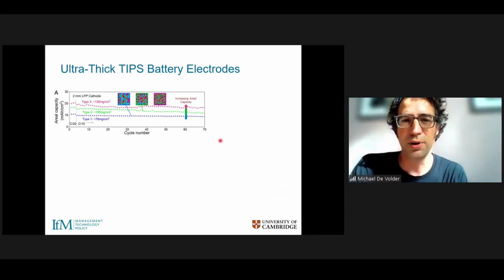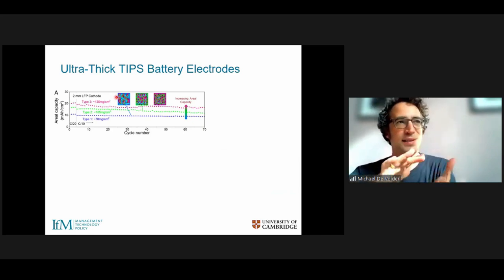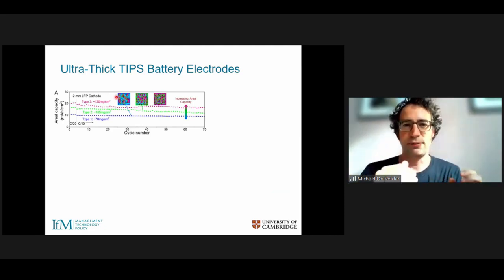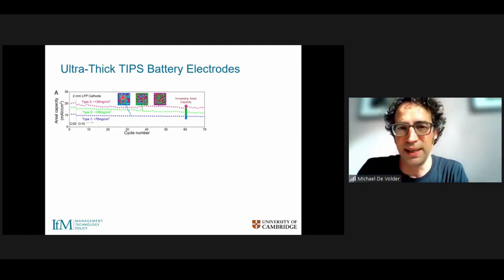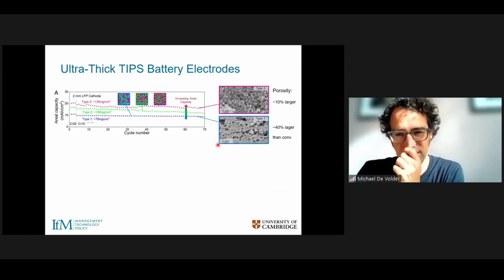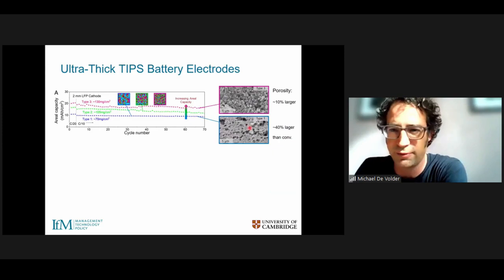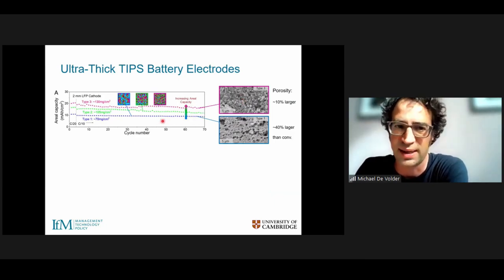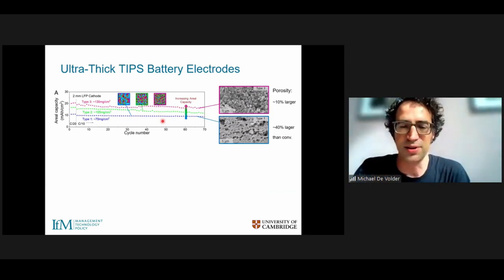And so what we've been working on next is taking our phase segregated squashy material and compressing it further to try and remove these big gaps in between our electrodes. It's maybe not very clear, but we start off with a material with fairly big black holes here. Those are the voids in which the electrolyte was located. And then by further compressing it, we were able to reduce those by 30%. So here we have a 40% larger void volume than a normal battery, and then here it's reduced by 30%, as I just mentioned. And that further increases the capacity. So we've squeezed out some empty volume.